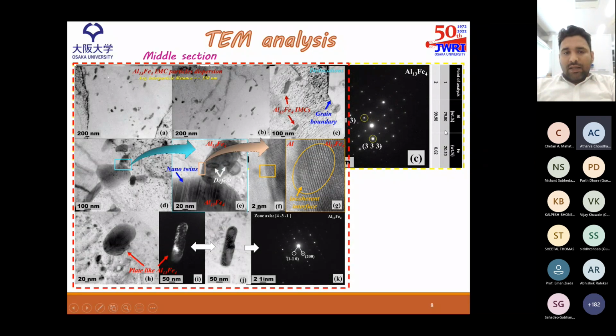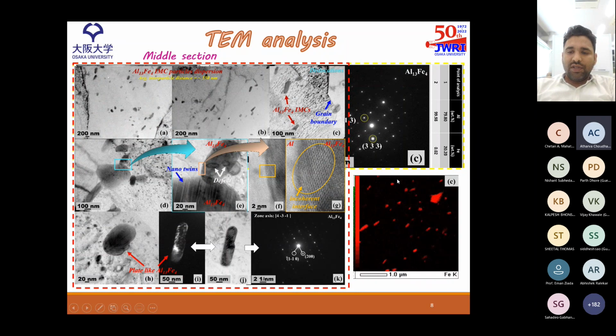The middle section of the AlFe alloy shows very interesting features. First of all, there's a homogeneous dispersion of particles, as can be seen with the EDS mapping here. And the other feature is there are two types of IMC particles that can be observed here. The first one is the elliptical one. This is the ellipse-shaped particle which we have observed. The others are the irregular ones. This is the irregular shaped IMC particle.